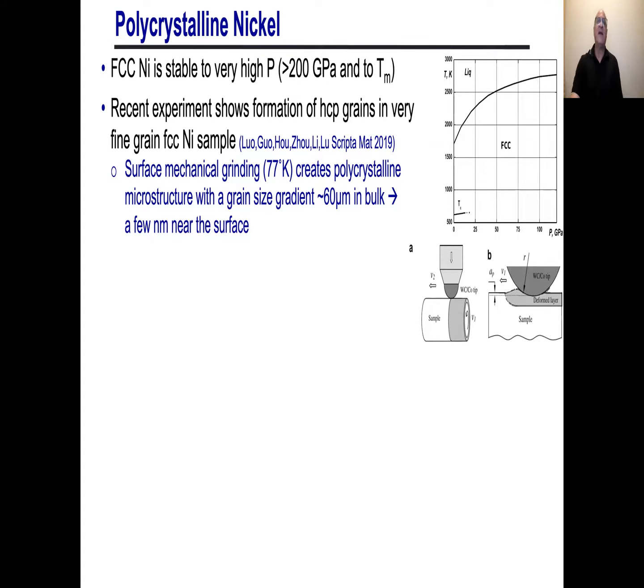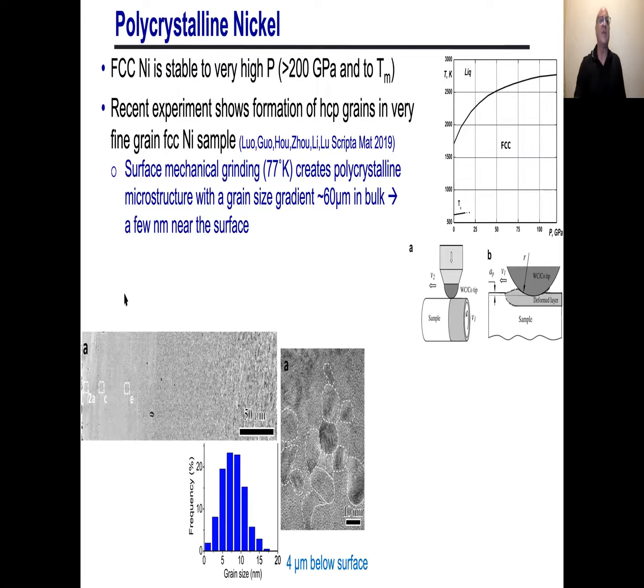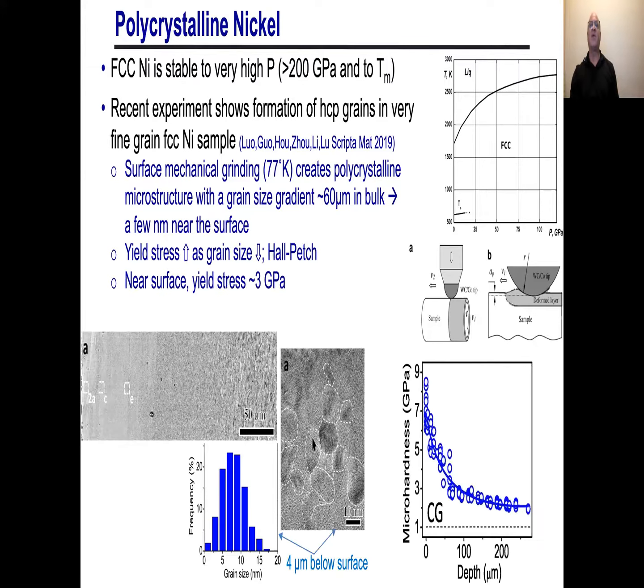Okay. Now, why do I bring that up? Well, it's because if you actually look at this sample, like the IMR group did, what you'll see is that some of the grains in the sample, entire grains, seem to be hexagonal close packed instead of FCC. Okay? And so here's some of the experimental observations. It's a little hard to see this, but this is just looking at the microstructure on a very large scale. If you look 4 microns below the surface, you can start to see small grains here, a little bit bigger than 10 nanometers, and a grain size distribution shown on the left.